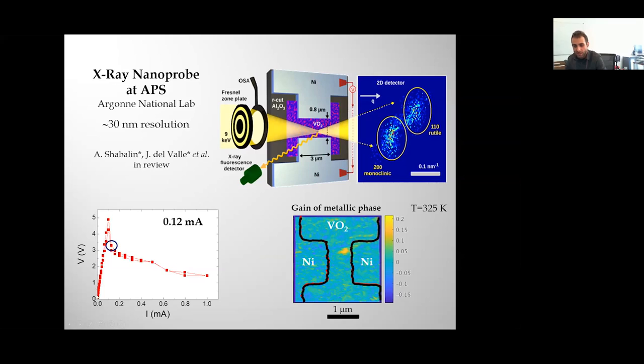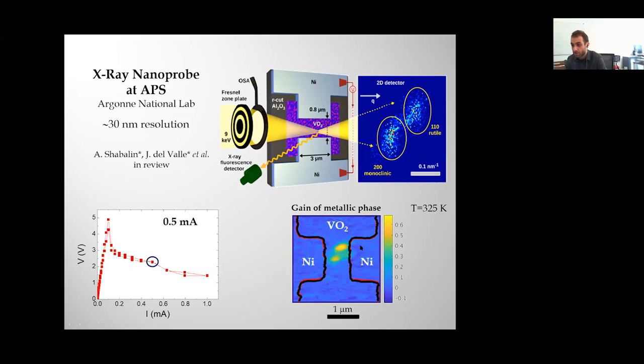So what you can see is that as soon as we pass the threshold voltage, we start nucleating some metallic phase. Here you can see this metallic area that appears there as a yellow spot. And as we increase the current that we apply, more and more spots are visible until a lot of the device looks like it has gone through the transition into the metallic state. But what you can see here is actually very different to what I showed you in the video.